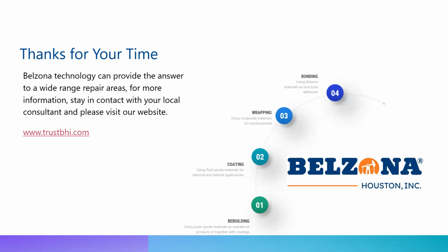Yeah, so that's definitely a topic. Our product is not going to handle fire. However, we do have testing where we put an intumescent coating on top of our product, and we went through the 60-minute fire endurance test. I think it's a fire at 2000 degrees F for 60 minutes, and then it's pressure tested after that, and it passed. So basically, you have to coat the composite with an intumescent coating that protects it and maintains the composite at a certain temperature throughout the 2000-degree fire experience. That makes sense. Yeah, exactly.